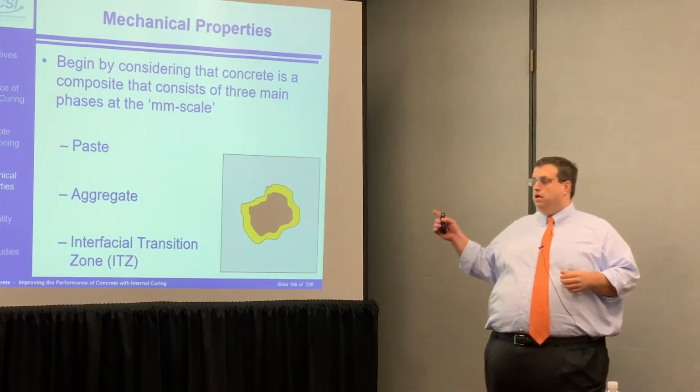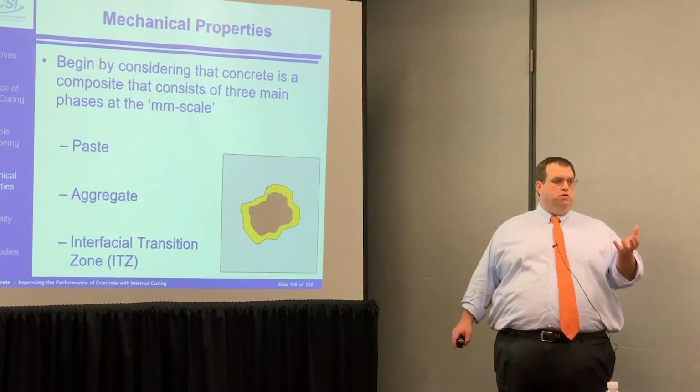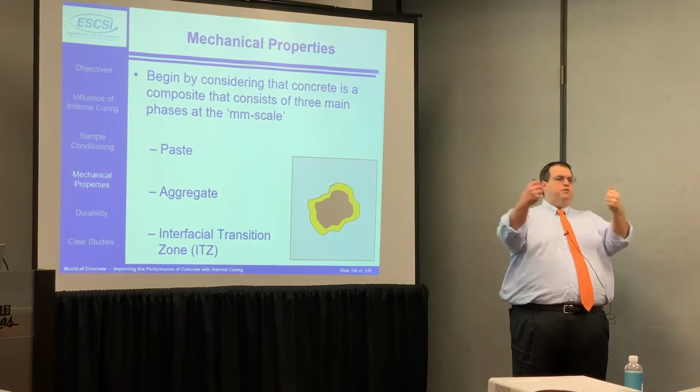The other thing that we've worked pretty hard, and I think we've now established, is most of these materials are siliceous. All right, or aluminous, but now you may look at that and say, siliceous, what the heck is that? It's not Sicilian, that's a whole different thing. Siliceous means that it's silica, they're silica containing materials. So it happens if you take calcium hydroxide and you put silica with it, you get calcium silicate hydrate, which is that good glue. So what's happening is, you're getting that silica from the aggregate reacting, but it's only reacting right at that surface, and it's really consuming that calcium hydroxide.